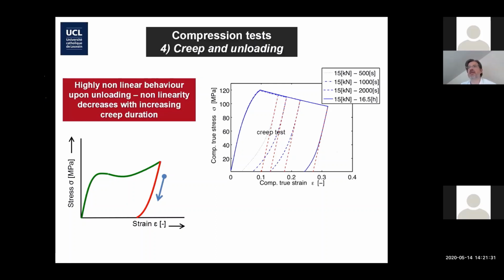Something more sophisticated. You load the material up to about 10%. And there you maintain the force. So you do a creep test. Of course, the material creeps, the true stress decreases because the material keeps deforming, and it's a compression test. Your section is increasing, so the stress is decreasing. So you do a creep, then you unload, and you see the unloading.